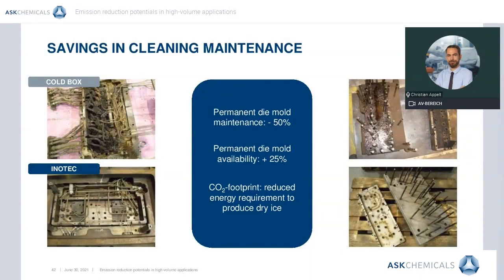When casting with inorganic sand cores, this costly and energy-intensive cleaning step is reduced by more than 50%. As a side effect, permanent die mold casting processes with inorganic bound sand cores are operated at lower temperatures compared to casting processes with organic bound sand cores, leading to a higher die mold availability of 25%. Furthermore, the time-consuming cleaning of the air systems is no longer necessary. The use of hazardous substances in the exhaust air purification system is also no longer necessary.